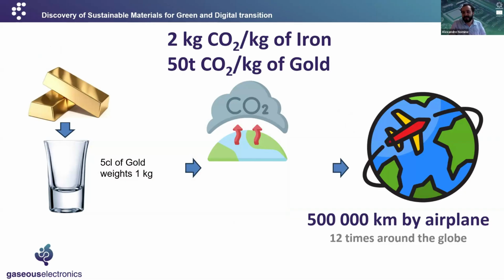You all heard, as material scientists, about the fact that the iron industry has to decarbonize. We had a very good talk before about aluminum, also about reducing the CO2 footprint. Well, you might be surprised, but actually iron is the cleanest one per unit of mass. As surprising as it might be, 1 kilogram of iron produces 2 kilograms of CO2. 1 kilogram of gold, which would fit in an espresso cup, produces 50 tons of CO2. So per unit of mass, iron is the cleanest. However, it is the most produced.